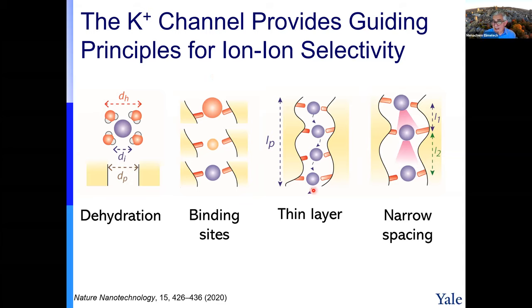You need to have a thin layer. If it's very, very thick, the transport rate of the potassium will be very low. But if it's very, very thin, also the sodium will go through. So you need to have the right thickness. And the potassium channel also has this unique thing that you have spacing of these functional groups in such a way that we have what we call the knock-on effect. This positively charged potassium pushes this one, which pushes this one, and they move through the channel. And I would like to show you some experiments that we have done.